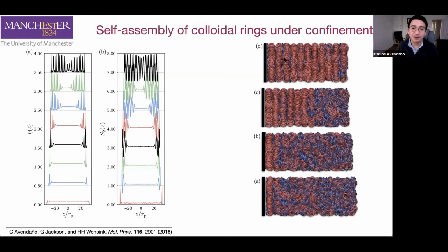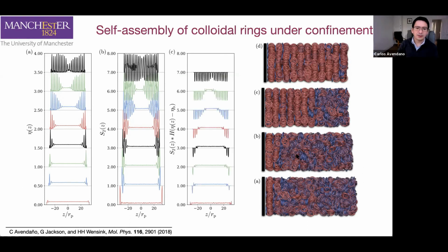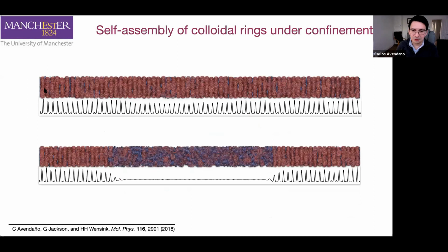And this is because the particles want to form always that asymmetric phase. And the only way to do it is by lying in a configuration that is completely perpendicular to the system. So this is not a normal behavior, but again, this kind of interesting or very weird behavior just arises from the non-convex nature of the particles. We decided to use very large systems just to make sure that all these results were consistent, and we observed that.